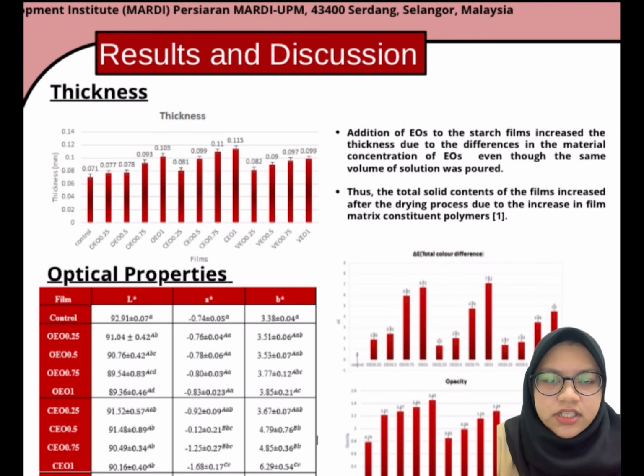Next, for the results and discussion part, first of all, the thickness was measured. Based on the graph here, it shows that the addition of essential oil to the starch film increased the thickness due to the difference in material concentration of essential oil, even though the same volume of solution was poured. Thus, the total solid content of the film increased after the drying process due to the increase in film matrix constituent polymers.